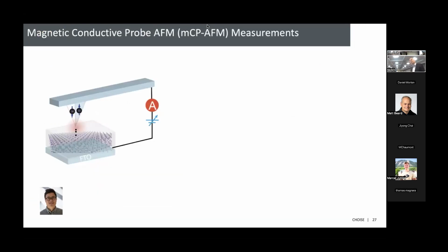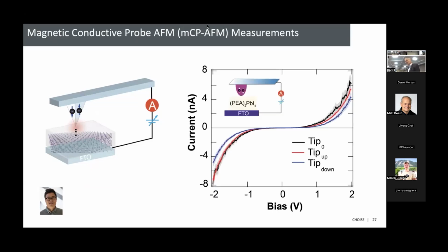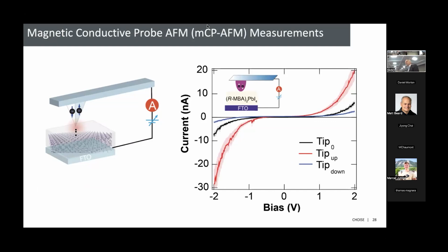It's a magnetic conductive probe AFM. You have an AFM tip that's magnetized, and then you measure current through it. And what Peng noticed here was that when he did this with the achiral version, it doesn't matter whether your tip is magnetized up or down, you get the same IV characteristics. But when you make this, say, R, and you have your tip magnetized up, then you have this low resistance state, high conductance. And if you have your tip magnetized down, keeping the chirality the same, you have a high resistance state. So you have two states.